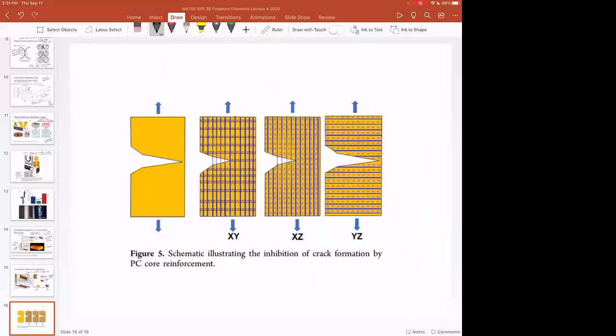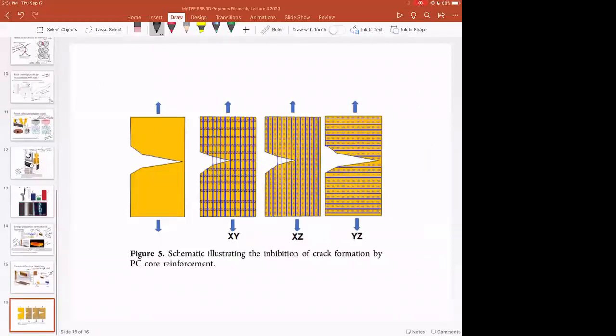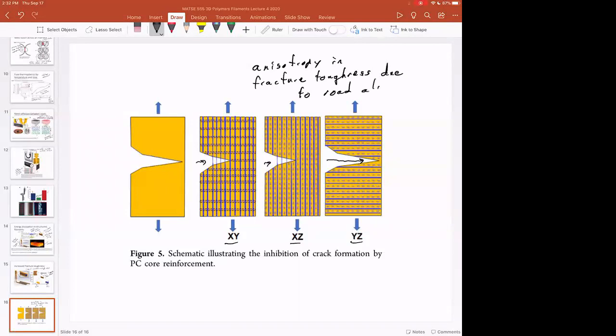And so there's really interesting stuff going on if you look at the anisotropy of this part, where you have in some geometries threads of polycarbonate spanning the crack, versus if you're going right through, you don't have any threads of polycarbonate spanning the crack. You have anisotropy in fracture toughness due to road alignment. And so that's interesting because of how this is printed.